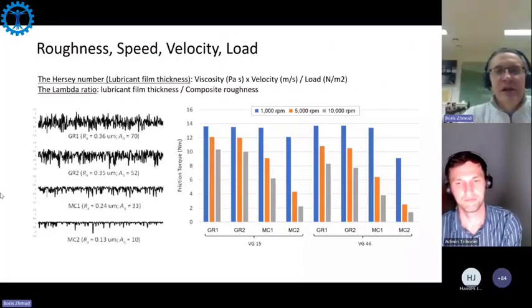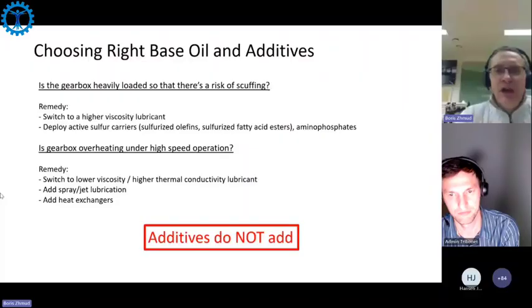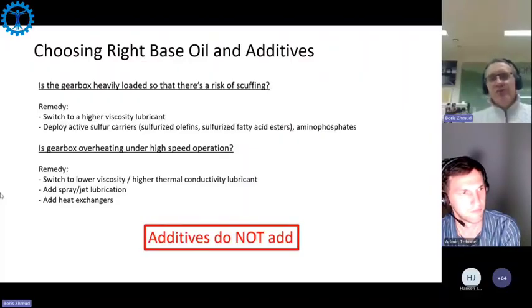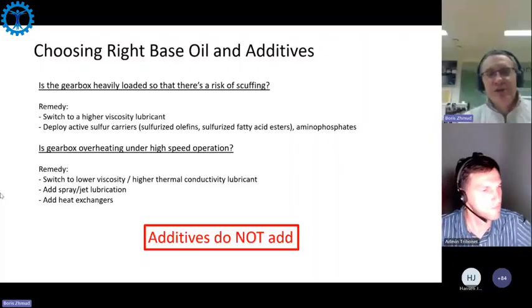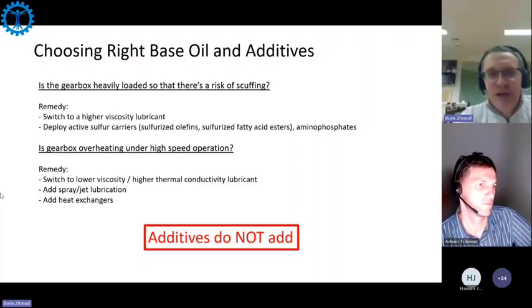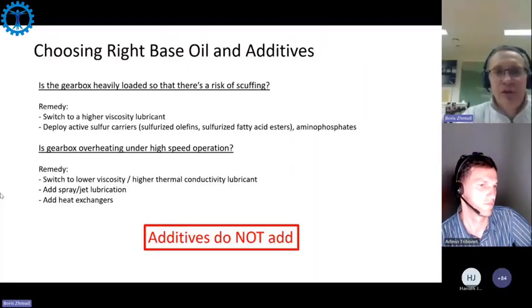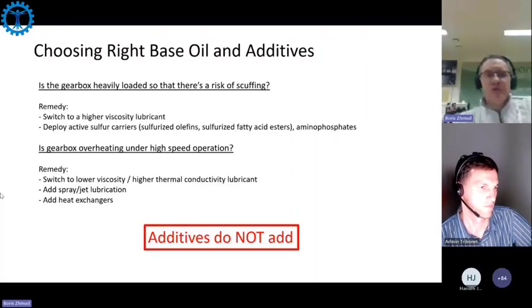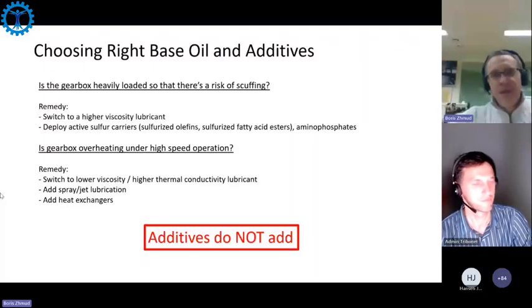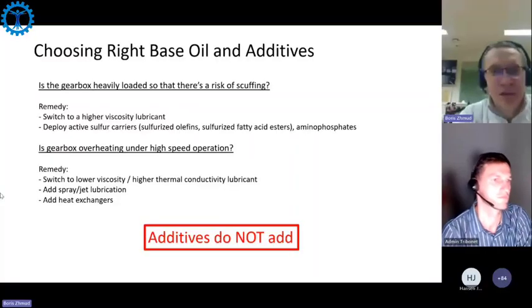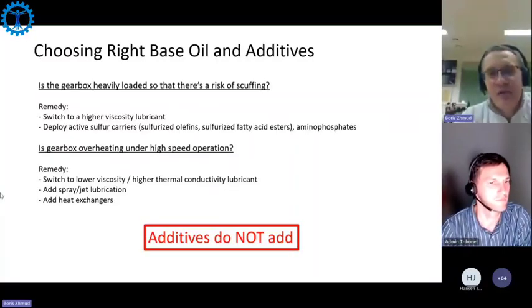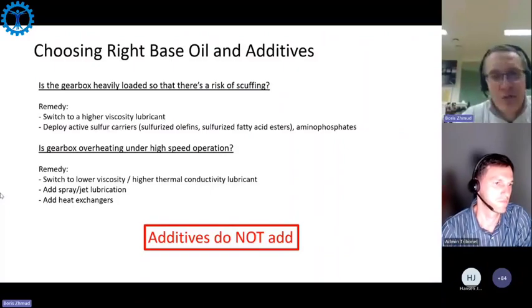It's also very important to keep in mind that there is no silver bullet. There's no technology which addresses all possible application scenarios. There's no additive which will play magic. So you always have to think about each individual case and find smart solutions. For example, imagine a gearbox that is heavily loaded and you have a risk of scuffing. What would you do? You should go to higher viscosity lubricants as the first remedy, not lower viscosity. For a low speed, heavily loaded gearbox, you need to increase viscosity. You need to deploy an anti-scuff additive: sulfurized olefins, sulfurized fatty acids, amine phosphates, or whatever.